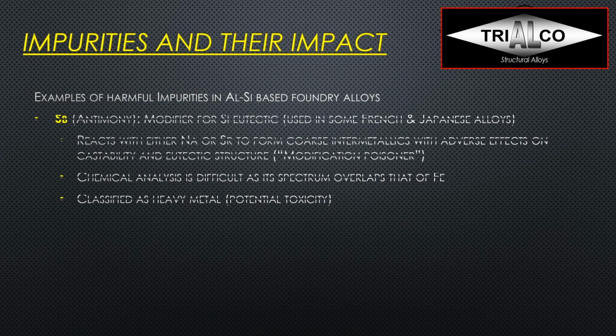Other examples, antimony, and this would be another nice modifier for the silicon eutectic, and it doesn't fade, so that's why it has been used, or was used in the past mainly, in certain French and Japanese alloys, even in some wheels that we can still find in the North American market, so you better want to separate them out. It reacts with sodium and strontium to form intermetallics with adverse effects on castability and eutectic structure, so it's actually what we call a modification poisoner.